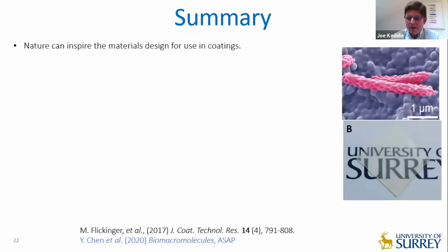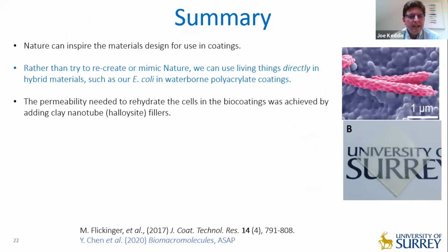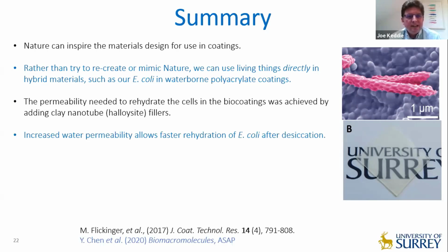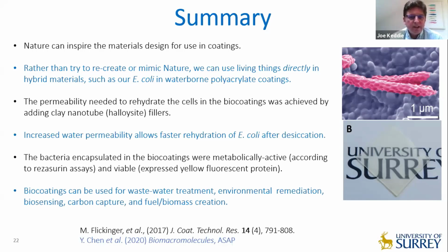Okay, so with that, I'll summarize, and I hope I showed you that nature can inspire coating design, but rather than mimicking nature, we just use nature, or living things, directly in a waterborne polyacrylate. It needed permeability, which we achieved with the clay nanotubes, and then we were able to get rehydration after the desiccation of the E. coli. They were metabolically active from the assays, and they were viable because they expressed the yellow fluorescent protein.